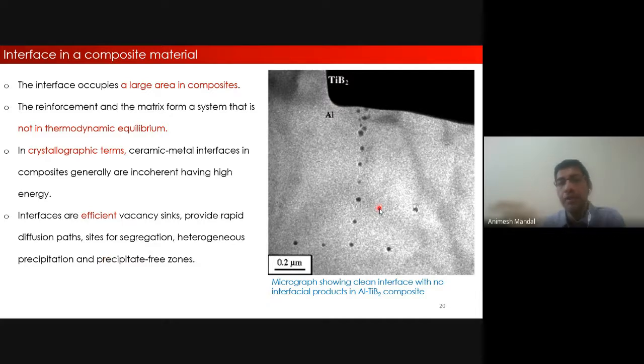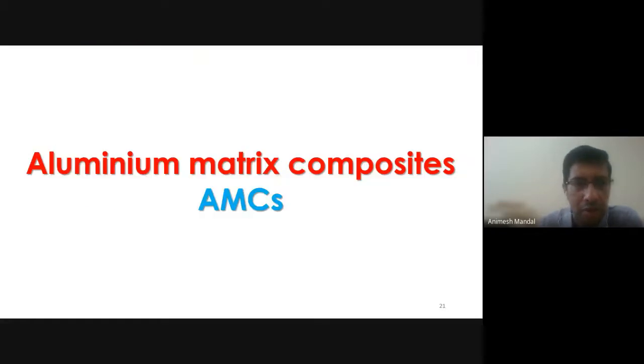Also, when we talk about wrought aluminum alloys or heat treatable aluminum alloys, you'll have precipitates, right? The interface also alters the precipitation sequence in these alloys. So you need to understand the importance of the interface in your metal matrix composites, because it can influence the properties quite significantly. It's not only about the matrix and the reinforcement, but also the interface. Whenever you choose any particular processing step, you need to be very sure that you do not form any interfacial products whatsoever. That's very, very important.